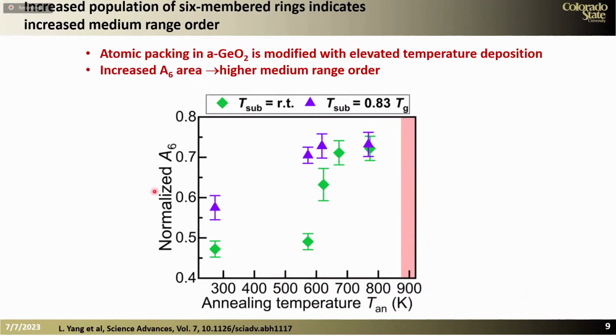So here I show you how the area of the A6 peak, which indicates the population of 6-member rings, is affected by the deposition temperature and by the growth temperature. And what we see is that when we deposit close to the glass transition temperature, we can actually gain in improving the medium range order.